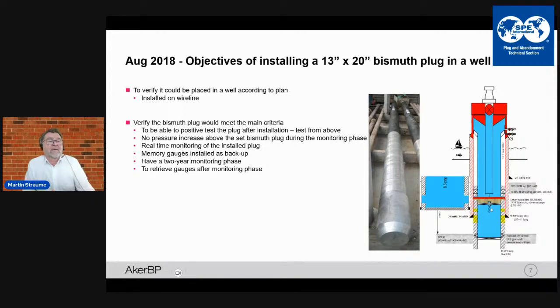let the gas go through up underneath the bismuth plug, which was set in a section milled area where we milled away the 9 5/8 casing and the 13 3/8 cement in the annulus. We had also allowed gas to come up this annulus and up underneath the same bismuth plug, so we had two potential sources of gas. I only showed this to show that we had milled a section window, which is not easy to see where the red bismuth plug is.